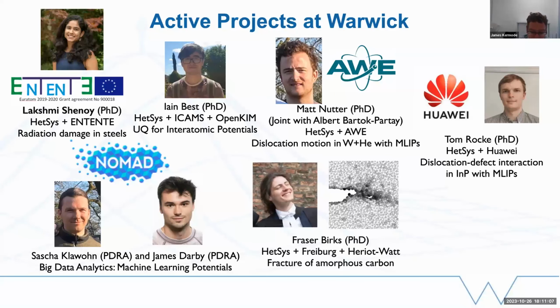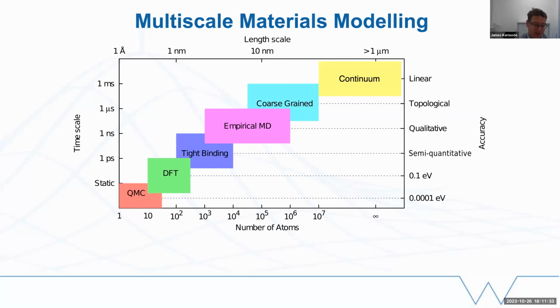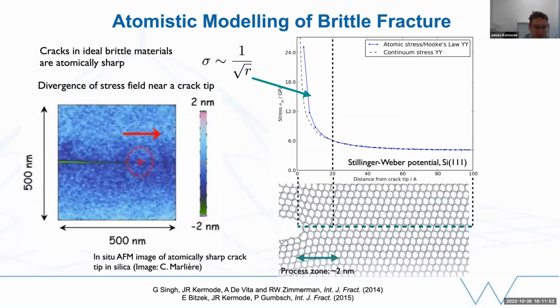So thinking about how we tackle these chemomechanical problems, as I sort of intimated in the introduction, we've got a range of techniques at our disposal, ranging from fully quantum, fully accurate things down at the bottom end of this hierarchy, up to more approximate, but more applicable approaches that can be used for very large systems. And if we want to understand something like fracture, the first idea would be to use something which is capable of describing a sufficiently large system that the boundary conditions don't overly determine the result. So we might think about using atomistic modeling with interatomic potentials. We can, in principle, use a big enough system and long enough timescale. However, the challenge is getting sufficient accuracy to describe bond breaking or chemical processes. And until recently, this was very difficult to do with the previous generation of interatomic potentials.